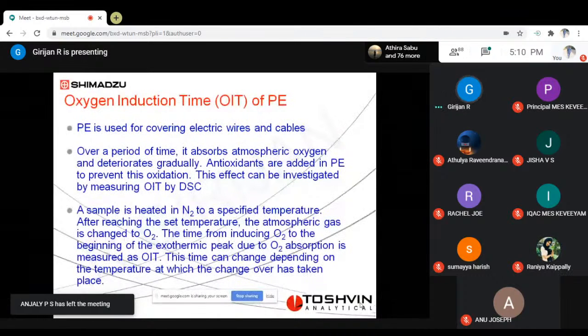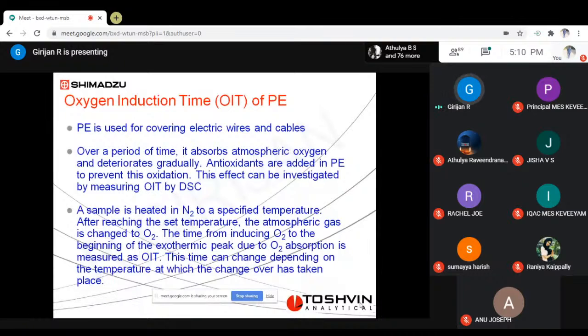And we measure the time from introducing oxygen to the beginning of the exothermic peak. So what happens when you start heating again is that the sample will undergo oxidation at one point of time because of the effect of oxygen and the effect of temperature. Whenever oxidation takes place, you can expect an exothermic peak. So the moment you introduce oxygen, start counting your time, and the time up to when the exothermic peak starts coming is known as the oxygen induction time. This oxygen induction time depends on the starting temperature. Instead of 180 degrees, if you change to some other temperature, the OIT will change. So this time can change depending on the temperature at which the changeover has taken place.